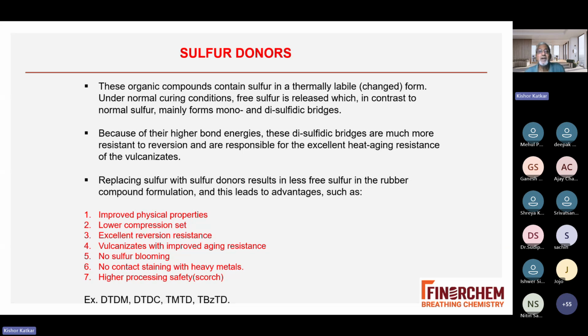Under normal curing conditions, free sulfur will be released, which, in contrast to normal sulfur, will give only mono and disulfide bridges. That is why many times the normal sulfenamide accelerator is replaced by a sulfur donor in order to get mono and disulfide bridges and higher scorch safety. Because of their higher bond energy, these disulfide bridges are much more resistant to reversion and responsible for the excellent heat resistance of the vulcanizate. Replacing sulfur with a sulfur donor results in less free sulfur in the rubber and leads to advantages such as improved physical properties, lower compression set, excellent reversion resistance, vulcanizates with improved aging resistance, and no sulfur blooming, provided it does not get exposed to higher temperature.